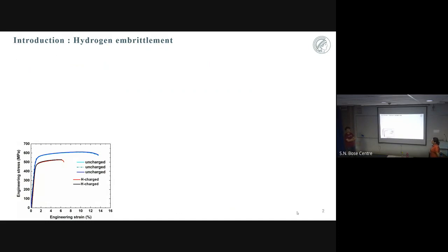In other words, you examine the end product, which is already damaged, which is absolutely interesting and useful information. But on the other hand, the evolution to this damaged condition is itself interesting, and I don't know whether experimentally, I'm sure they can monitor this. Yes, they can do it experimentally. The problem becomes that such evolution before the damage cannot be done by DFT at least. It can be shown by MD. Yes, it can be done by MD, but not by DFT. You do MD and then make an analysis on the MD structure. That's definitely possible. Of course, you have to do an MD.